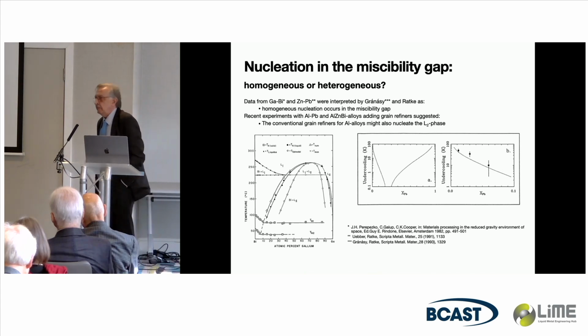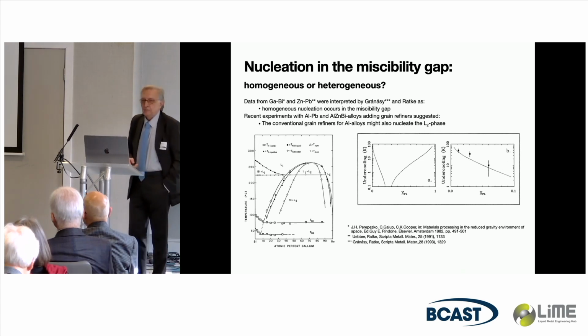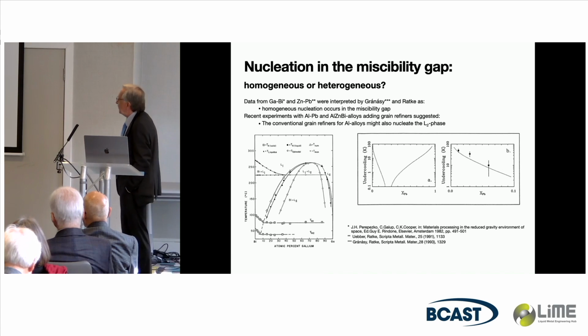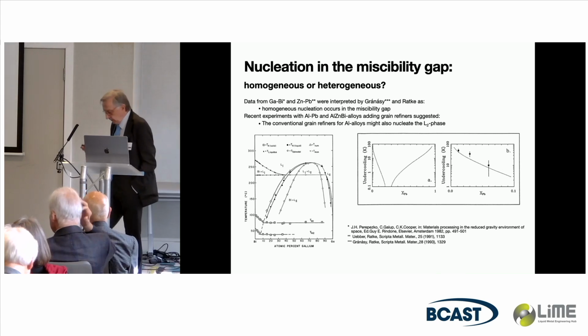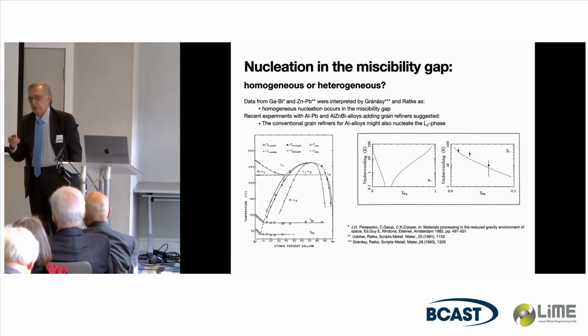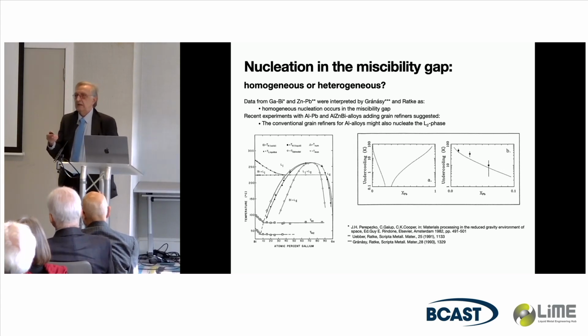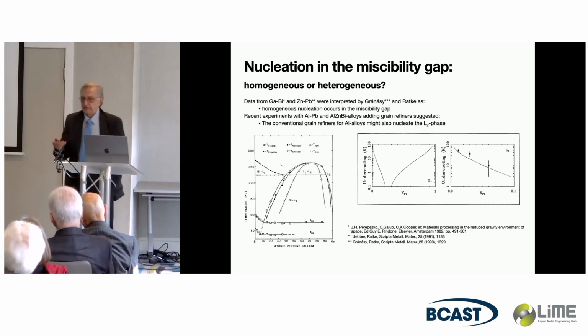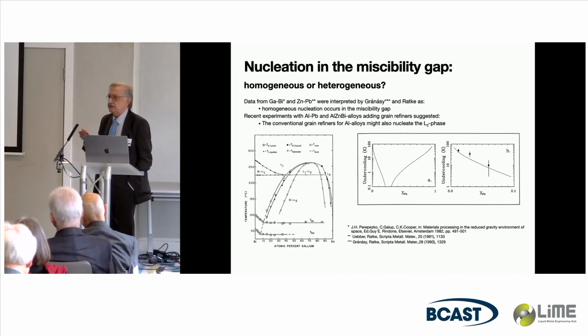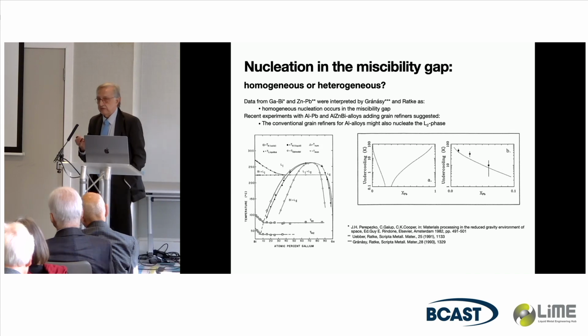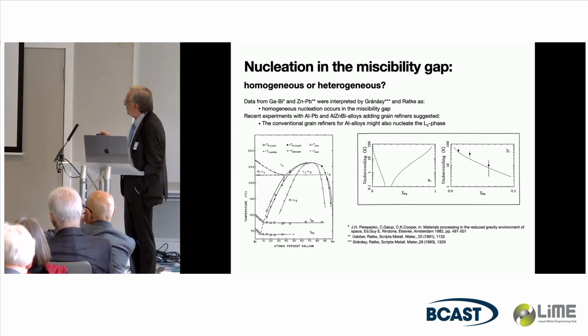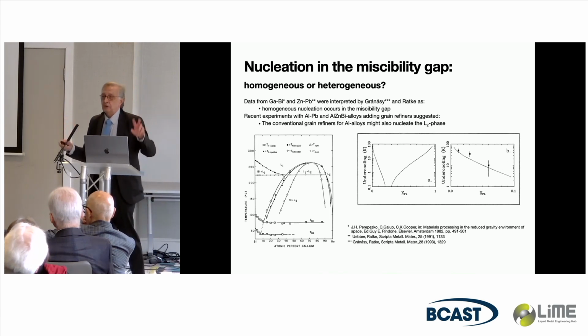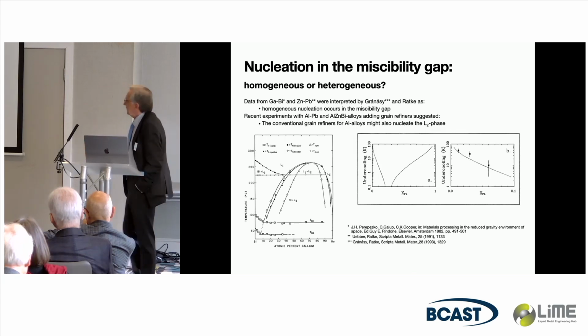There's a very old paper, 1982, that's 40 years old, made by John Perepezko and his co-workers, and they measured in gallium bismuth undercooling with DTA, which is not so easy to do because the phase separation, or the nucleation of these droplets, makes only a small thermal event. So you must have a DTA with a high resolution in enthalpy. This is possible. We built our own DTA at that time, not a commercial one. We built it just to measure a very small thermal event.